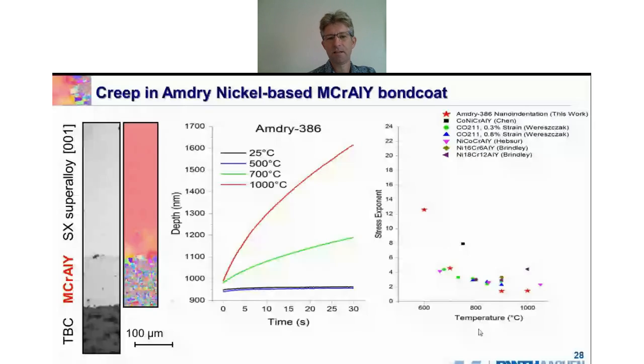But sapphire indenters work well, and this is some work from Aachen, and thank you very much to Sandra Korte for supplying this slide. This is the bond coat between the thermal barrier coating and the superalloy substrate. This is just looking at the creep that occurs in 30 seconds, and we can see at 500 degrees it's very creep resistant. If anything, the creep is slightly less than at room temperature. But then at higher temperatures, you can see a very high creep, and this limits its application temperature.